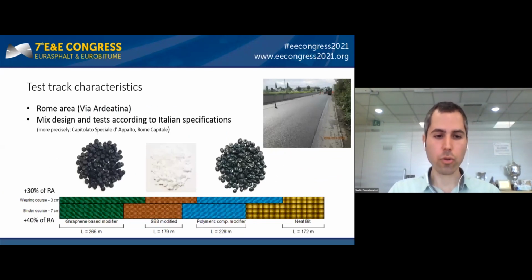Here you can see the plot showing the trial section that was done during this research. This trial section is located in Italy, in the Rome area, via Ardeatina. The trial section consisted of both bearing course and binder course. Here I'm going to present just the bearing course test results. As you can see in this plot, the trial section was divided into 4 different sections. The first, graphene-based modifier; the second, SBS modified mixture; the third, a comparable elastomeric polymeric compound modified mixture; and finally the neat bitumen.